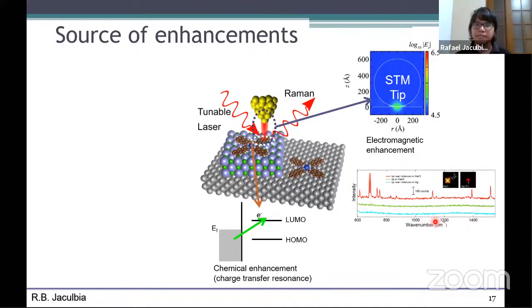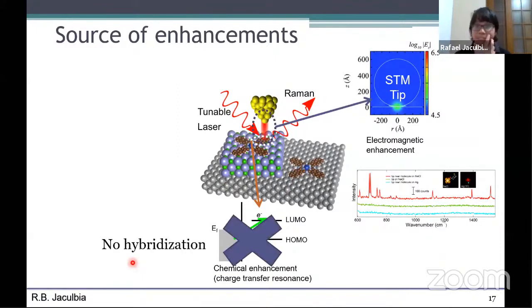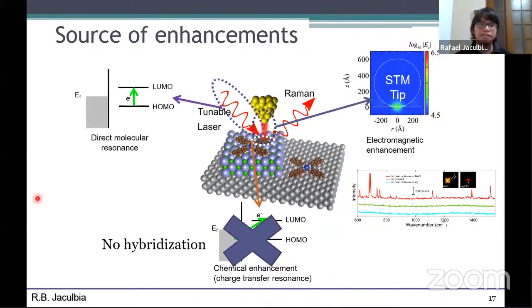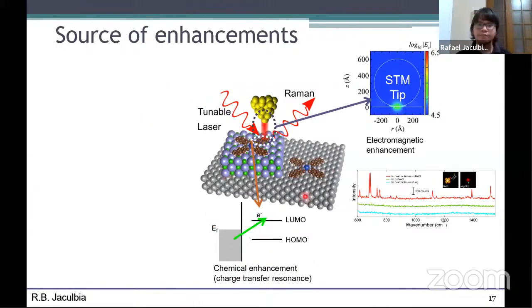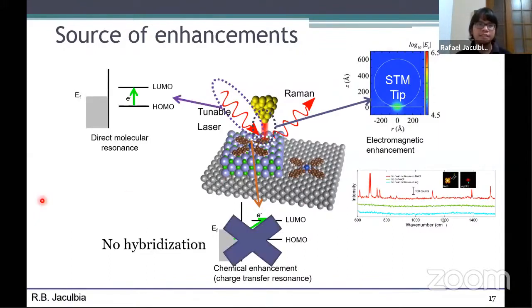Also, chemical enhancement cannot be the reason, because as I said, there is no hybridization. So there is no charge transfer channel between the metal and the molecule on NaCl. The chemical enhancement is absent, or if not really absent, it's very much reduced. So to explain our results, one more possible reason is direct molecular resonance. That is, instead of charge transfer, we excite the molecule directly by choosing the proper excitation light.